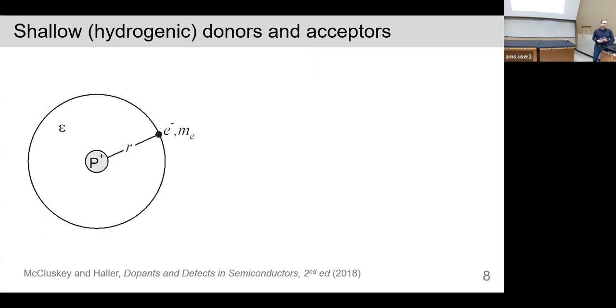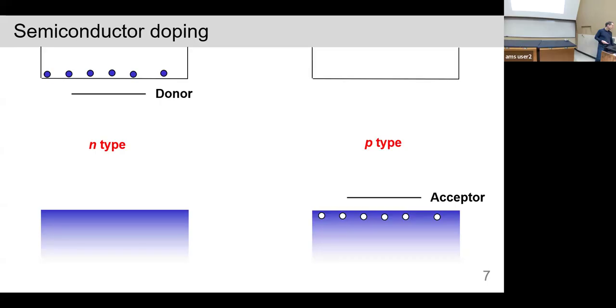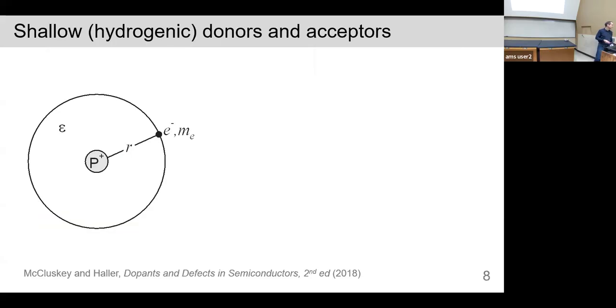Now, if you want to make a device that operates at room temperature, you want this energy to be pretty small so that the thermal energy is enough to promote the electron. And so that gets us to shallow, or so-called hydrogenic, donors and acceptors. This is an example of phosphorus in silicon. So phosphorus has that extra electron. The electron leaves the phosphorus, but it orbits around in a hydrogen-like orbit. So it's just like the Bohr atom.